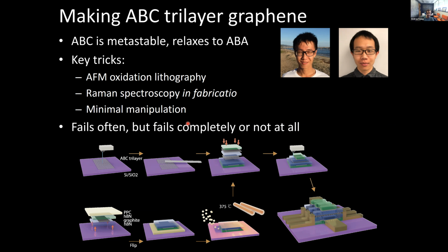And this is particularly in contrast to moiré systems, which have been kind of in vogue the last few years, where you're really trying to stabilize a structurally unstable stacking order when you have a finite twist angle. That's not even metastable, it's simply structurally unstable.